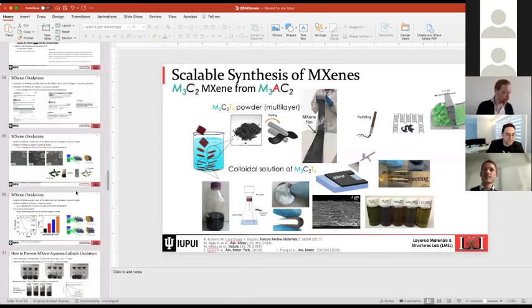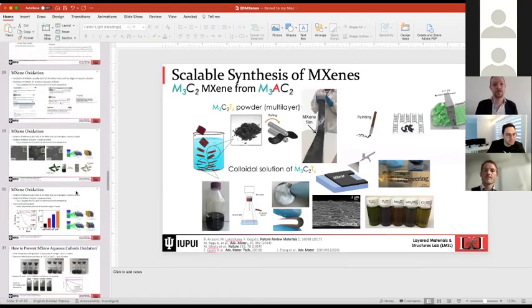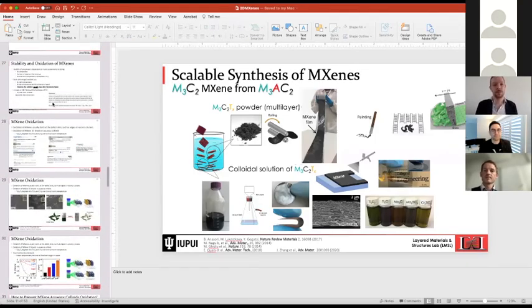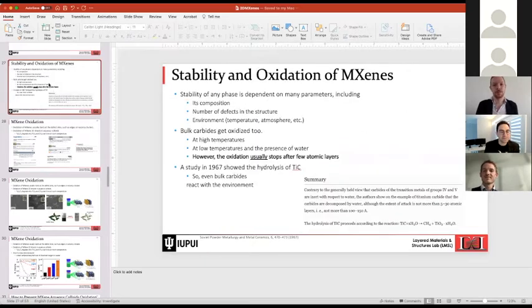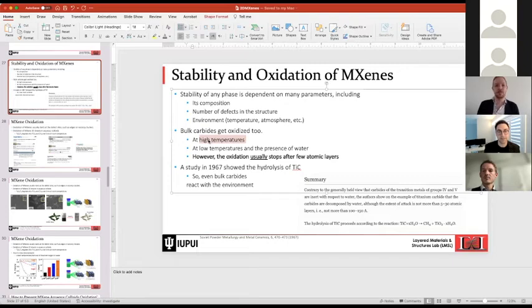So as I usually like to mention, everything gets oxidized, right? Including us. So even the highest stable carbides, right? Titanium carbide, molybdenum carbide, or all the heating elements that we work with, the furnaces that we have in our labs, they all oxidize. Now, the stability of all of these high temperature phases depends on how thick an oxide scale we form around these to protect and prevent further oxidation.